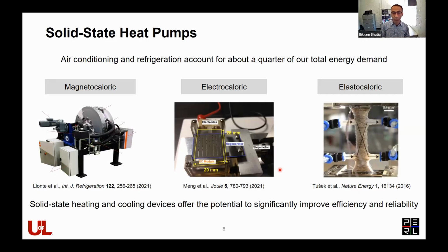Then you have electrocaloric, which has shown a lot of promise in the last few years. There have been device demonstrations which have shown high COP values and power densities. But again, it is mostly suited for applications that are small scale, so typically chip cooling kind of applications. It's not necessarily scalable. Elastocaloric has shown a lot of promise in the last few years. Again, it mostly utilizes NiTi alloy, or nickel titanium alloy, which is put under tension and compression. Again, there have been some device demonstrations with promising performance reported, but the problem with these NiTi alloys typically is that they don't withstand a lot of tension compression cycles, so they have a finite fatigue life, and so they are not able to withstand millions of cycles that you would want from a commercial heat pump device.